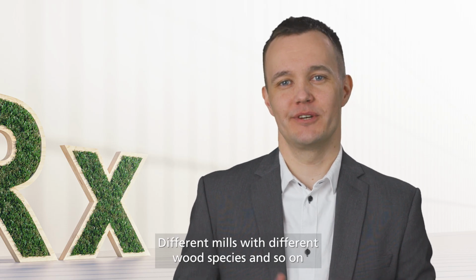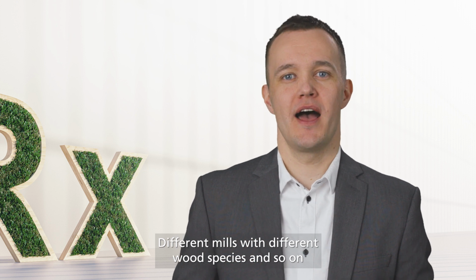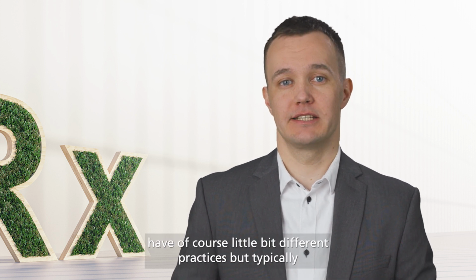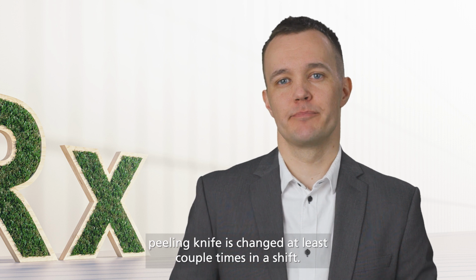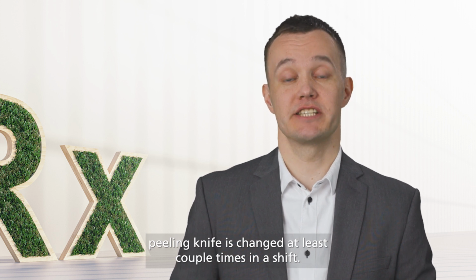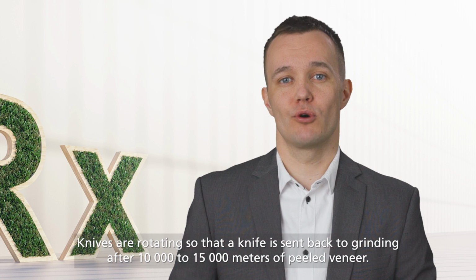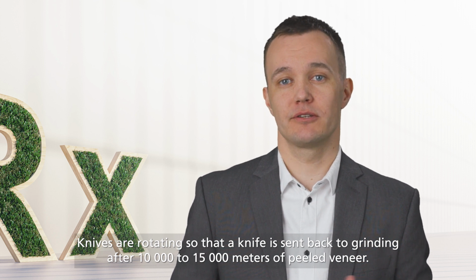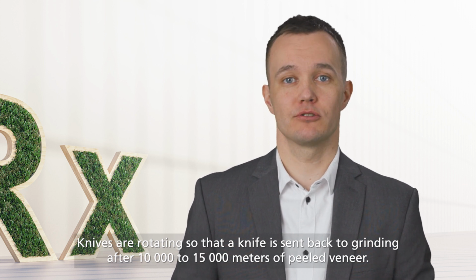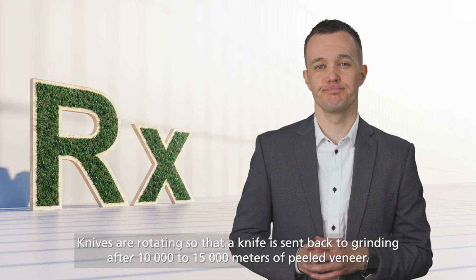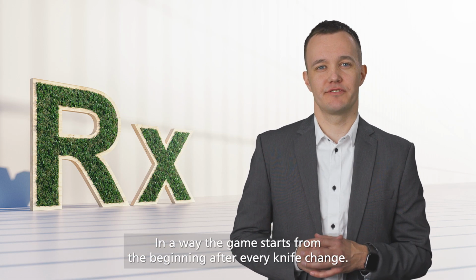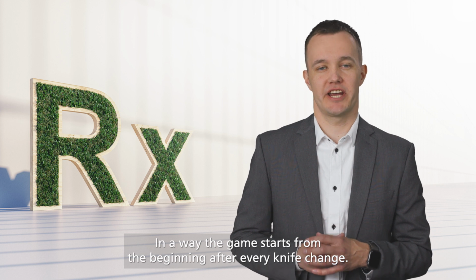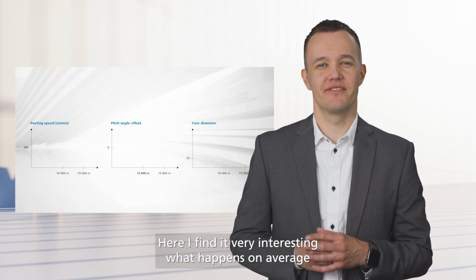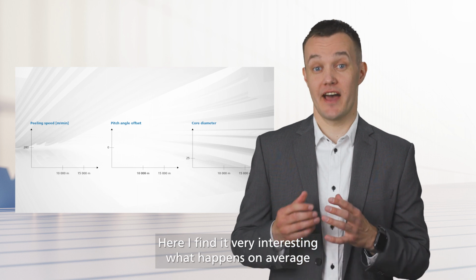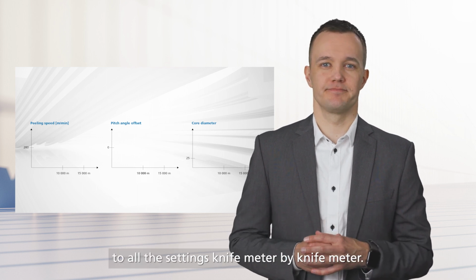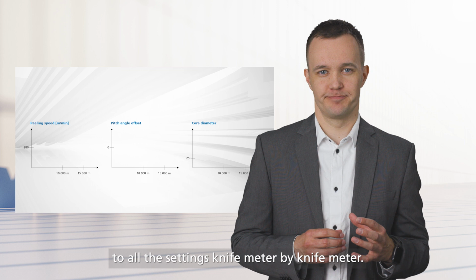Different mills with different wood species and so on have of course a little bit different practices, but typically peeling knife is changed at least a couple times in a shift. Knives are rotating so that a knife is sent back to grinding after 10 to 15,000 meters of peeled veneer. In a way, the game starts from the beginning after every knife change. Here I find it very interesting what happens on average to all the settings, knife meter by knife meter.